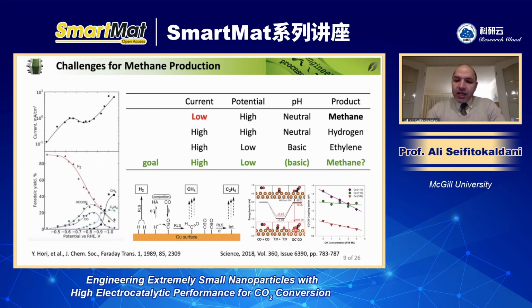We describe why, in basic environment, carbon-carbon coupling becomes easier, and you can produce multi-carbon products such as ethylene much more easily. And since you are working in basic environment, the electrolyte that you're using is even more ionically conductive, so you don't really have to apply a very large potential to achieve a high current density. So you can achieve high current density at lower potential in basic environment, but then the problem is, as we described here, since CC coupling is easier, you produce mostly ethylene and you can't produce methane.